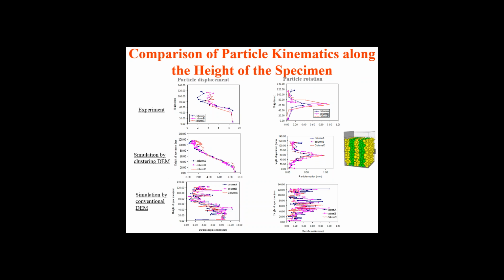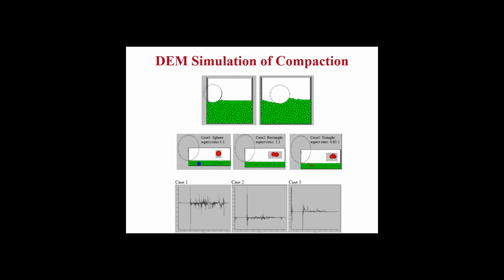And correspondingly, the particle rotation is also not consistent if you use the conventional DEM approach. You can see this random kind of movements, but the experimental is showing some kind of pattern, and also the strain localization in there. And using the simulation by the clustering DEM approach, you can achieve this objective. So for compaction, we also use this compaction DEM modeling, incorporating different types of aggregate shape in there. Look into different aggregate shapes, how the aggregate shapes affect the compaction effects.